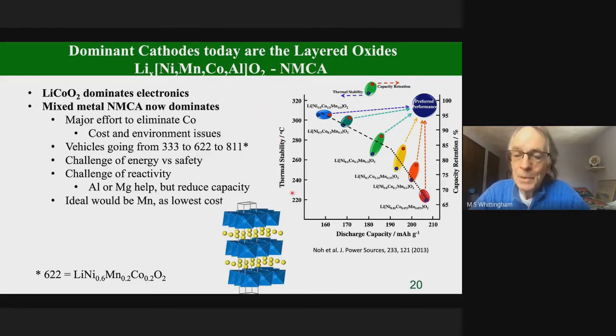So let's just look at the thermal stability. If we take these materials, the most thermally stable one only has 1/3 lithium in it. It has the lowest capacity, 160 milliamp hours per gram. If we want to get up above 200, then we have to go to higher nickel. This one is 85%. And you can see its thermal stability is 100 degrees lower. Though we hope the lithium batteries never get to this temperature, the thermal stability is a measure of how reactive these materials are with the organic electrolyte. So if they react, we lose capacity. So this directly relates to this capacity retention on the right-hand side. And our goal is to get into this blue box: high thermal stability, high capacity, and high capacity retention.